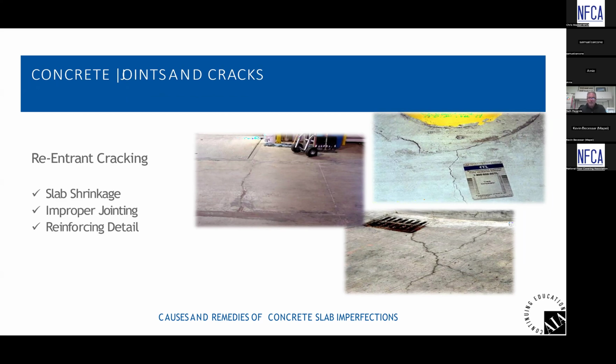You go to the bottom right picture, that is a crack that's coming off an outside corner of a drainage grate. That crack off the outside corner is called a re-entrant crack. Technically, there should have been a saw cut there coming off the corner in all four corners, because as the concrete dried and cured and dried along both sides of that, you get movement, you get shrinkage movement there, and there should have been a saw cut there. There wasn't, so the concrete created its own saw cut in the form of a crack going in whatever direction it wants it to go.